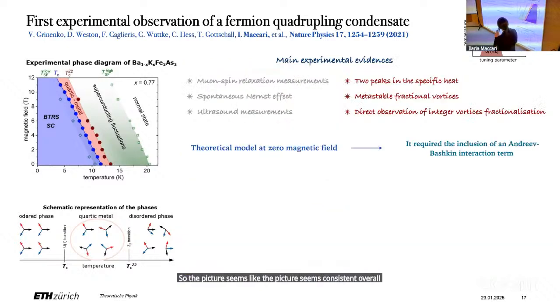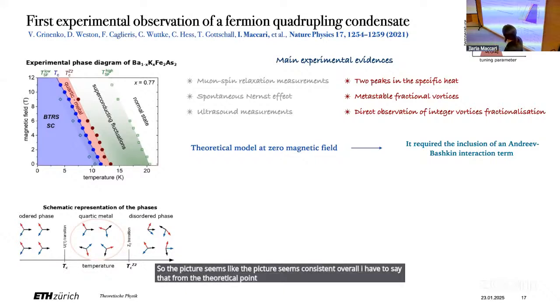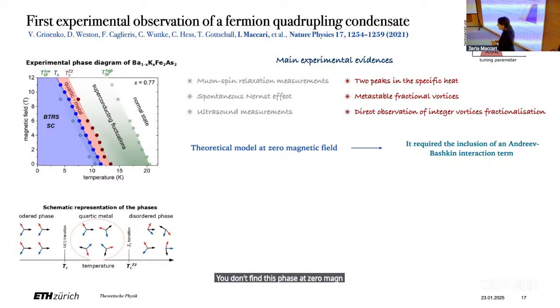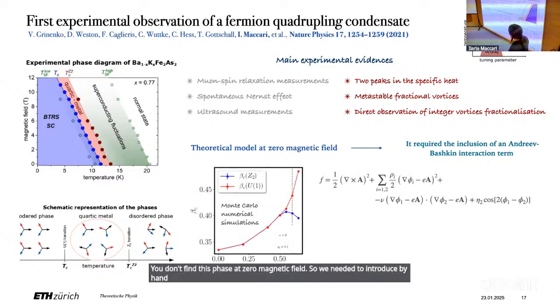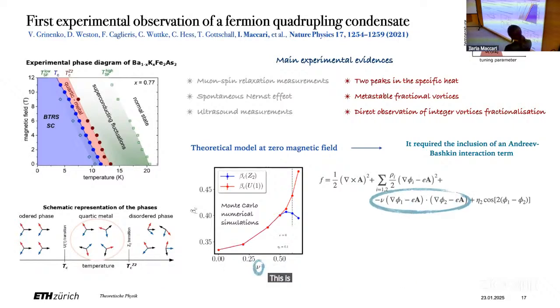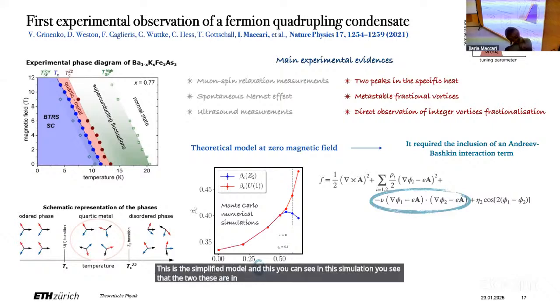I have to say that from the theoretical point of view, it was not trivial to stabilize this phase. If you take just the more standard, let's say, three-band Ginzburg-Landau model, you don't find this phase at zero magnetic field. So we needed to introduce by hand another interaction between the components, which is a sort of drag interaction. This is the simplified model, and as you can see in this simulation, the critical temperatures are split when this coupling term is strong enough.